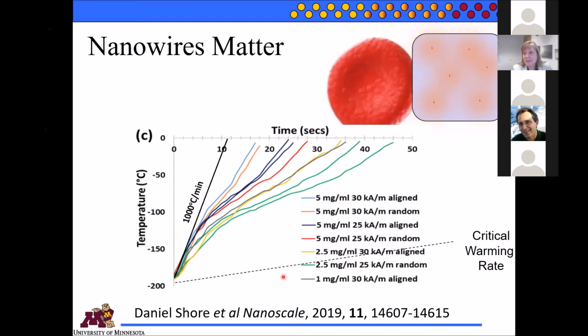Compared to the critical warming rate, it turns out that the initial rate for a lot of our wires, even at fairly low concentrations, is 1,000 degrees per minute. But to actually get up to the melting temperature, the rate slows down a little bit. This elbow right here is mostly due to the change in the C, the heat capacity of the cryopreservation agent as it goes from being a solid to a liquid. So that's why there's a little elbow here. But I think the key is that even if you take a look at the sample, which is half the concentration of the SPIONs I showed you earlier, we're still at 0 degrees C in less than 20 seconds. So we're really excited to actually optimize this now. This was kind of our first shot at it. And now that we have funding through this ERC in Minnesota, I'm looking forward to working on this application more.